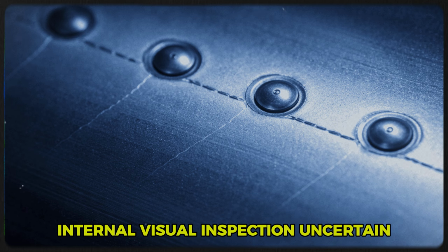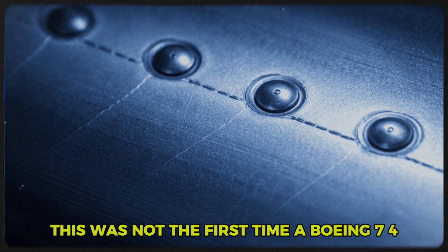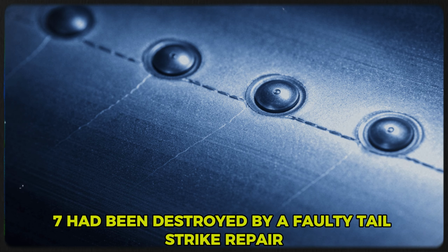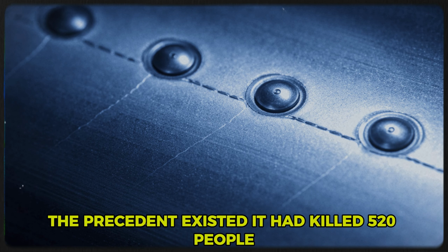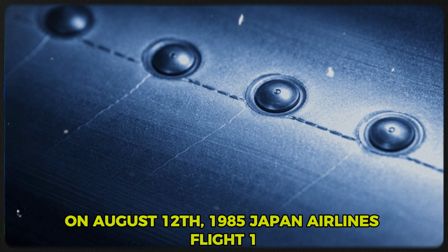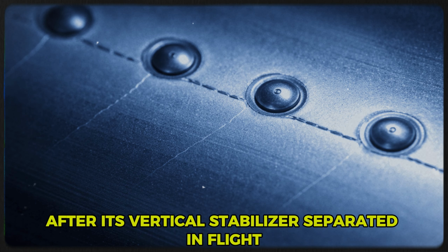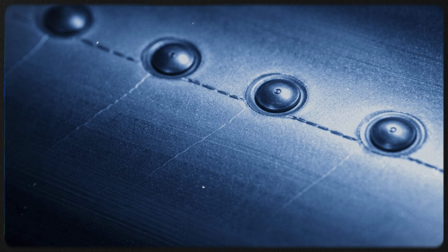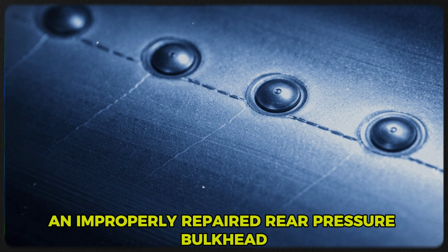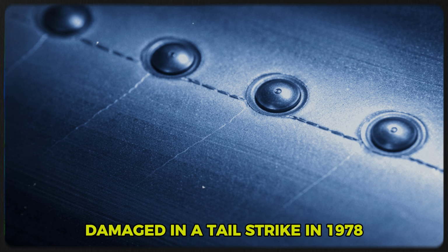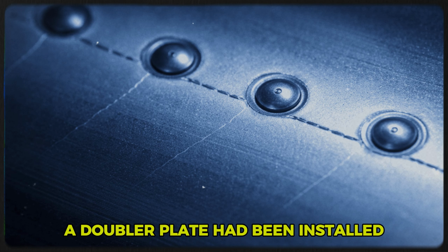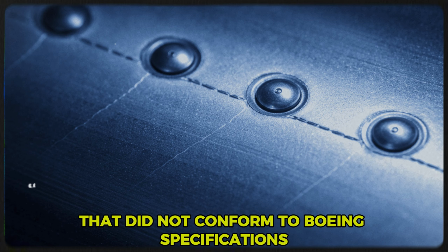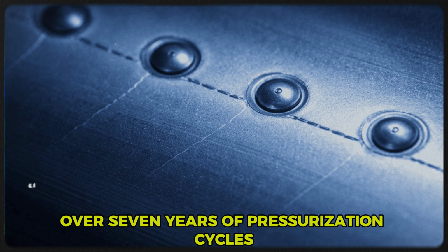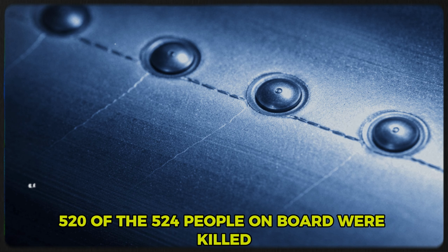This was not the first time a Boeing 747 had been destroyed by a faulty tail strike repair. The precedent existed. It had killed 520 people. On August 12, 1985, Japan Airlines Flight 123 crashed after its vertical stabilizer separated in flight. The cause was an improperly repaired rear pressure bulkhead, damaged in a tail strike in 1978. A doubler plate had been installed that did not conform to Boeing specifications. Over 7 years of pressurization cycles, the bulkhead failed. 520 of the 524 people on board were killed.